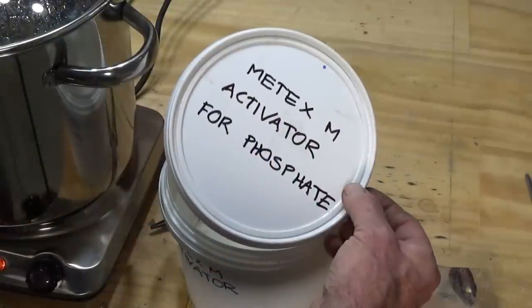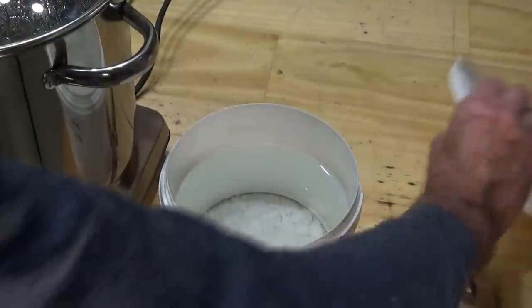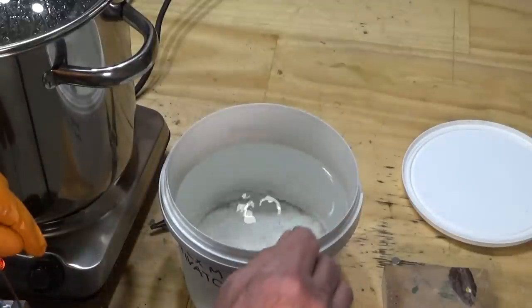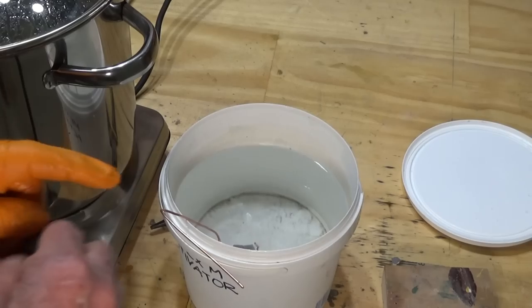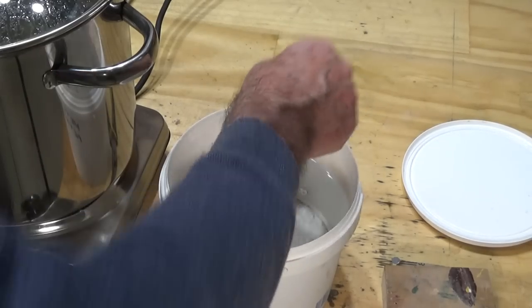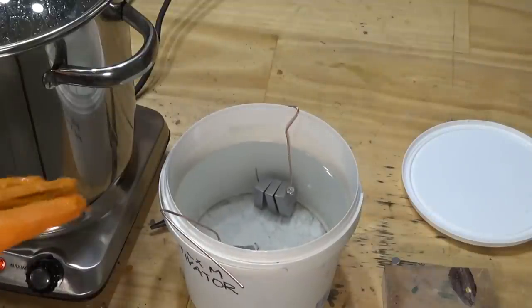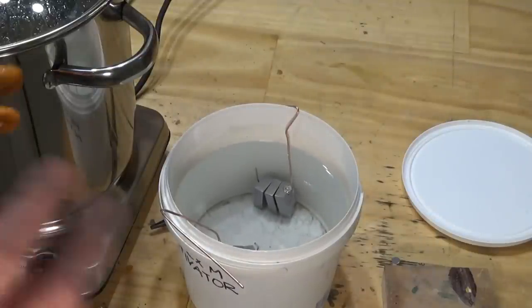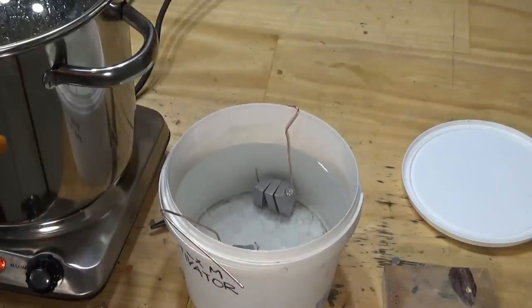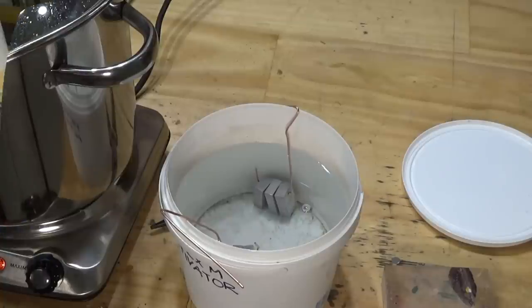Next step is to go into this Metex M activator for phosphate. Once again, this came from the Jane Kitts catalogue, and I believe it's an acidic process. So we're just going to let that sit in there for about 1.5 to 2 minutes. There's very fine bubbles appearing on the surface of the steel during this process, so that's what leads me to think that it's etching it in a certain fashion. And then we do a water rinse, and then we're going to boil the part in clean water for about a minute, and then it goes into the Parker phosphate solution.